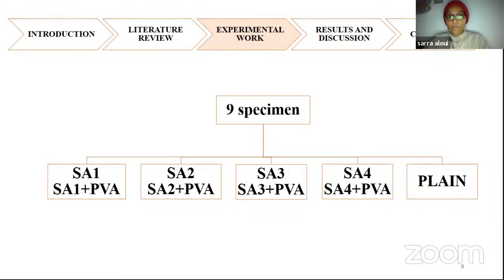To obtain the best results, 9 specimens were cast, named SA1, SA2, SA3, and SA4. For each of them, 2 specimens were cast. The first one contains just steel fibers, and the second one contains both steel fibers and PVA. The last one is named plain. It contains neither steel fibers nor PVA. It's done just for the controlling part.